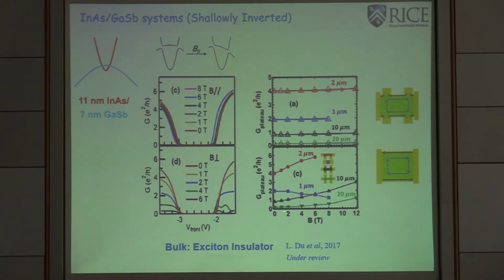Now what happens for these three? These three look like all the effect is to cause the conductivity to go up under perpendicular magnetic field. So that's maybe related to the formation of the chiral state instead of the helical state. Because under perpendicular magnetic field, you break time reversal symmetry. So the magnetic field will favor one branch and disfavor the other branch. Therefore, they are not completely cancelled with each other.